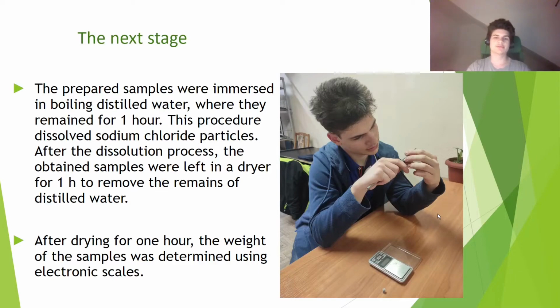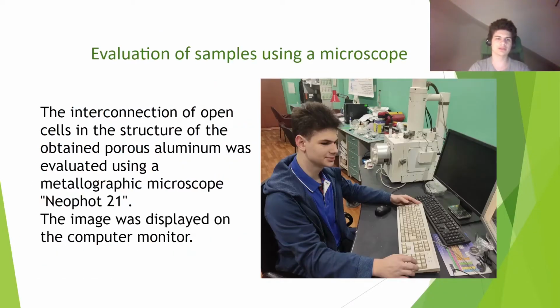The prepared samples were immersed in boiling distilled water, where they remained for 1 hour. This procedure dissolved the sodium chloride particles. After the dissolution process, the obtained samples were left in a dryer for 1 hour to remove the remains of distilled water. The interconnection of open cells in the structure of the obtained porous aluminum was evaluated using a metallographic microscope Neophot 21. The image was displayed on the computer monitor.